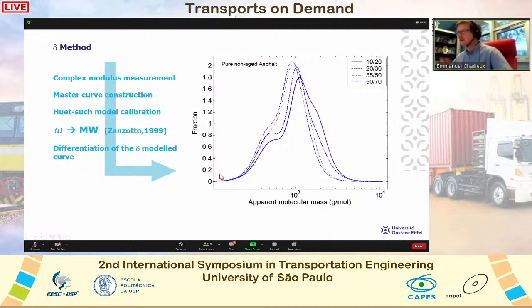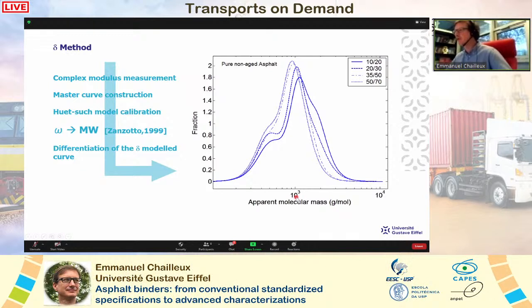So you see that we have a distribution centered around 1,000 grams per mole, and you see that the peak of distribution follows the grade of bitumen. Here we have a very hard bitumen, so we have more big molecules than the softer one, where you have more light molecules. So a good idea of the distribution.